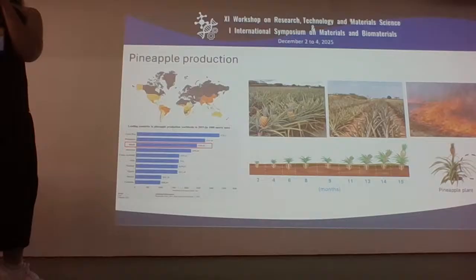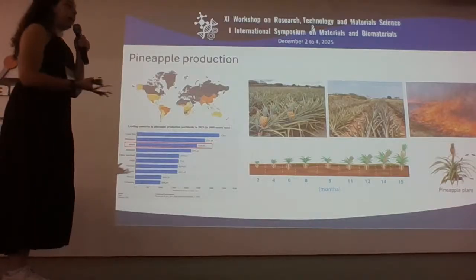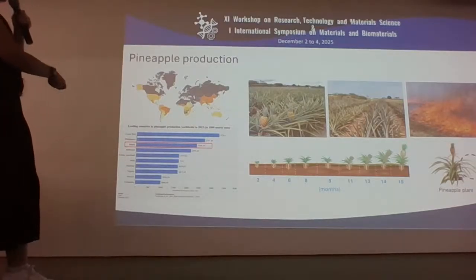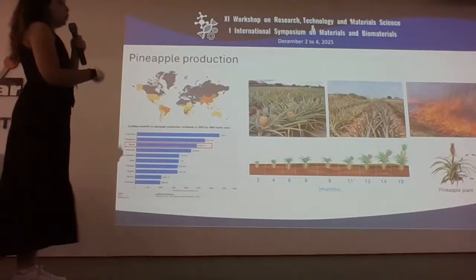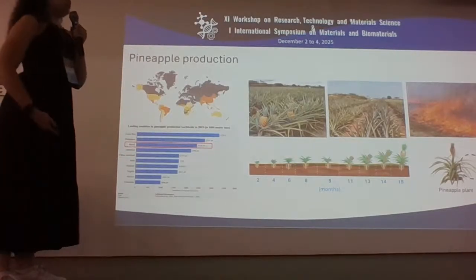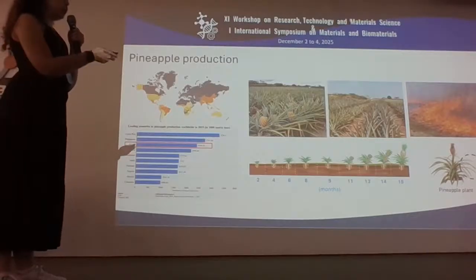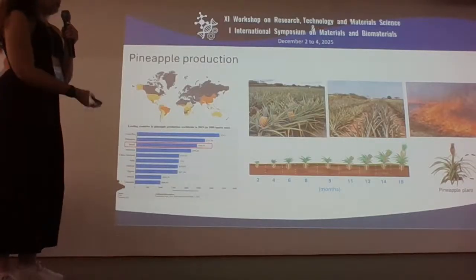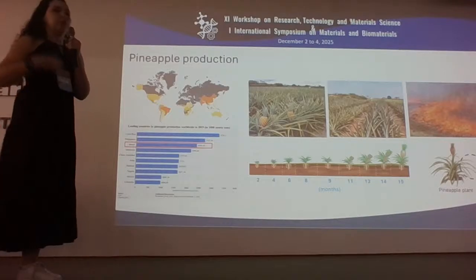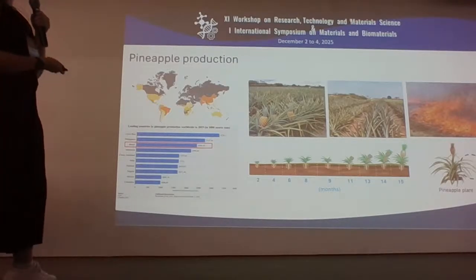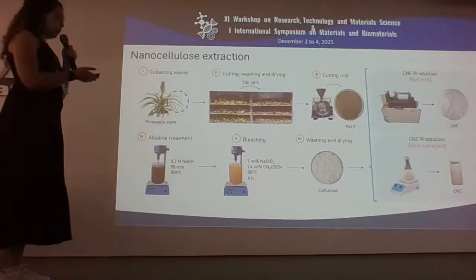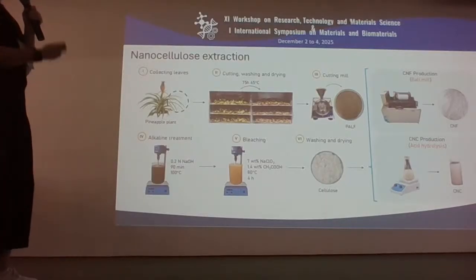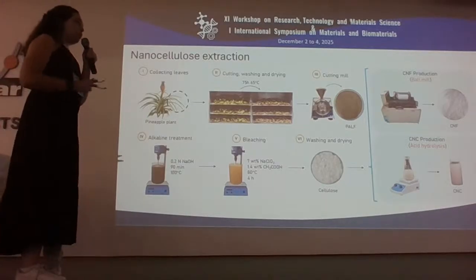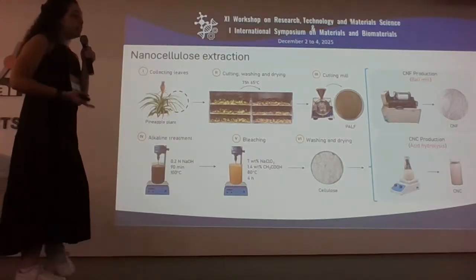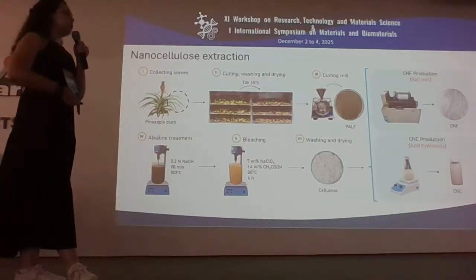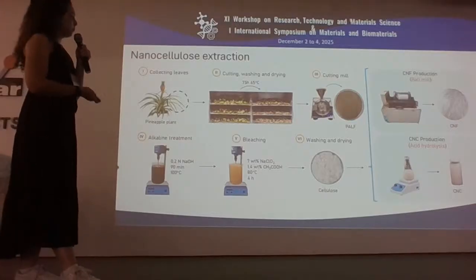So in the field of sustainable materials, we are working with pineapple leaves. Brazil is one of the largest producers of pineapple in the entire world, and usually after the harvest they burn the leaves. So our idea is to use the leaves from the bottom of the plant to extract the cellulose and produce sustainable materials. For the extraction of cellulose, we did a simple procedure of alkaline and bleach treatment. And we also produced 2 types of nanocellulose, the CNF and the CNC. The CNF by ball mill mechanical processing, and the CNC by acid hydrolysis.